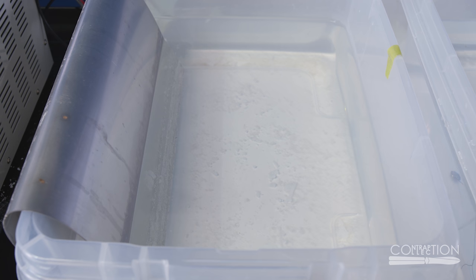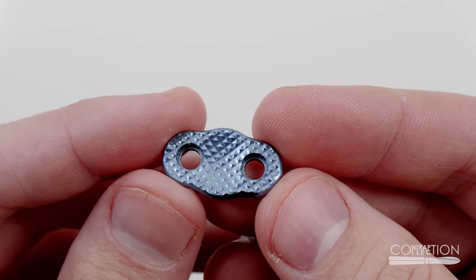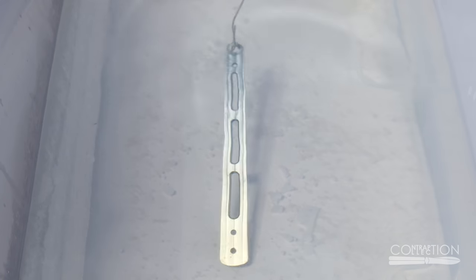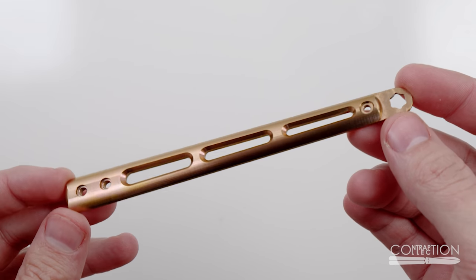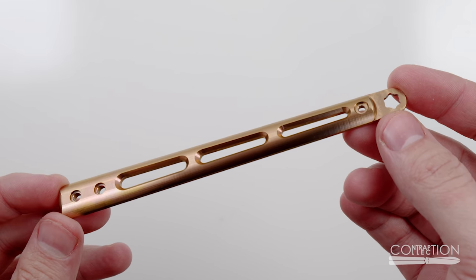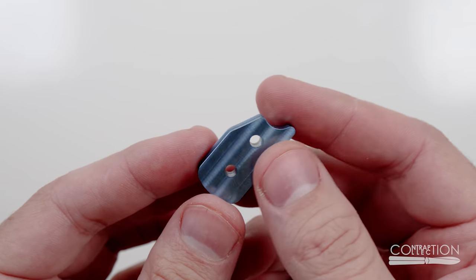I might as well anodize the parts too. I went with 33 volts for the buttons and spacers, 65 for the handles. I wanted to try to get a kind of rose gold color, and I thought light blue would go good with it.